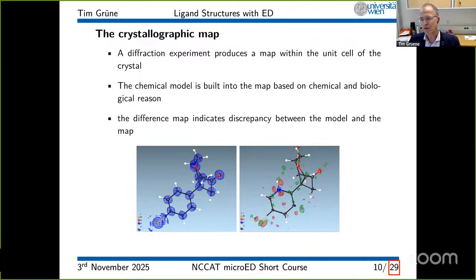One thing that's important when you have little crystallographic experience is what we actually look at. The map is what we get out of the experiment, and it's shown in two different types. The blue mesh here, at atomic resolution, is the direct map. It shows where the atom positions are, and the model should follow that map. And the red and green map on the right-hand side is the so-called difference map. The difference map shows the difference between the model and the data. The better your data, the clearer the difference stands out.